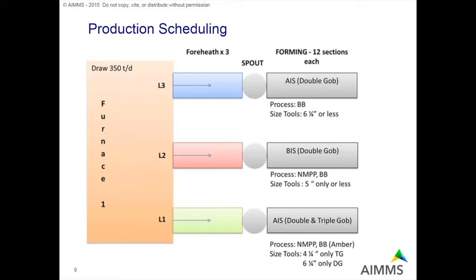Adding further complexity: if you want to change glass color — for example from green to amber or to transparent glass — you have to completely empty a furnace and fill it up with a new mix, which takes a couple of days. So that's not something you typically want to do frequently. As we'll see later with other examples, this scheduling is really different from other production scheduling activities.